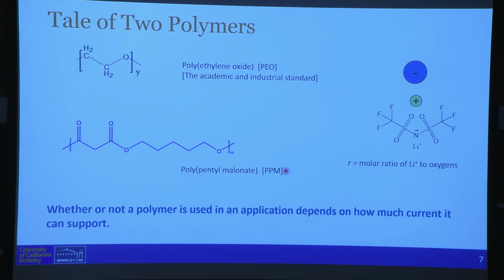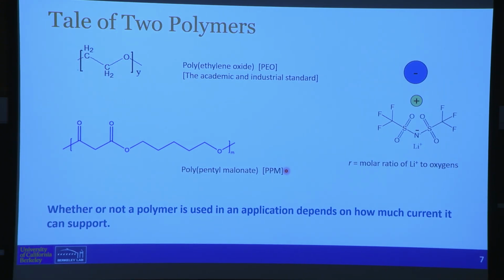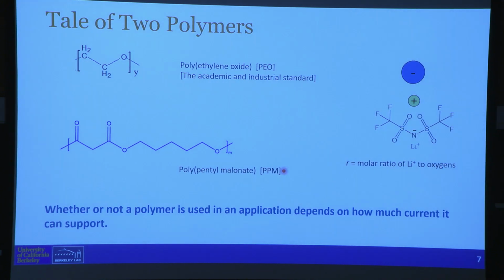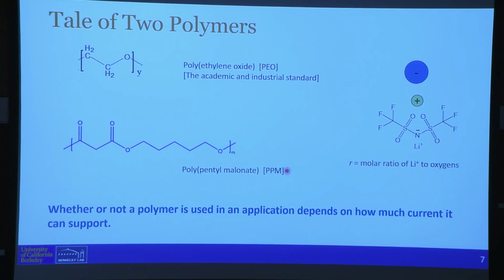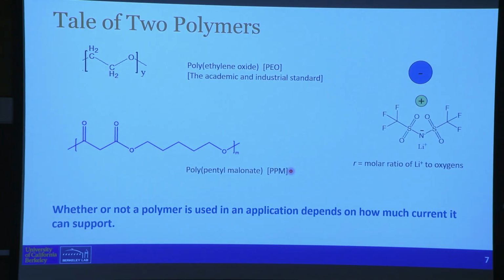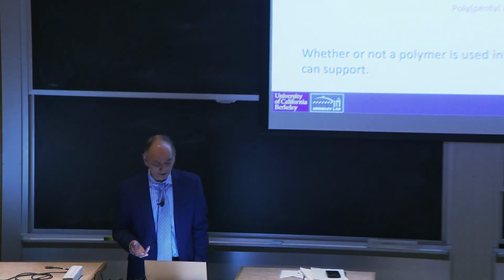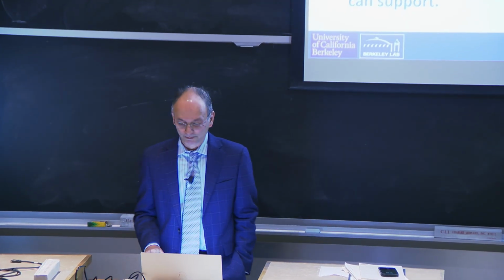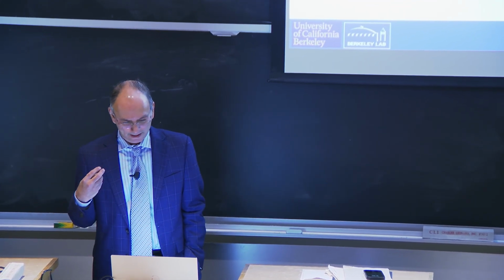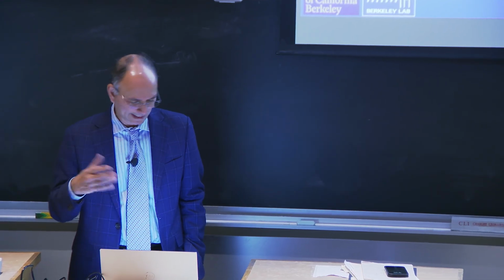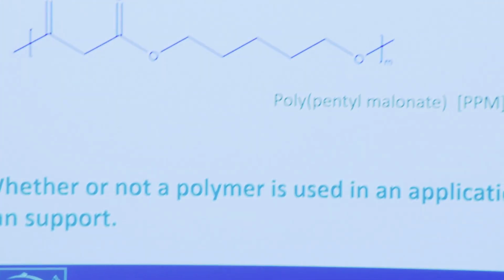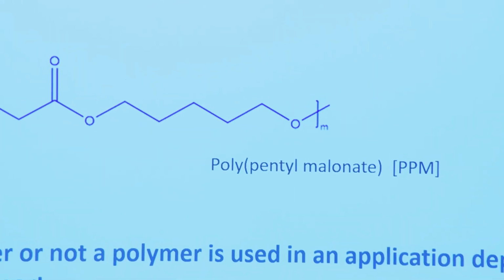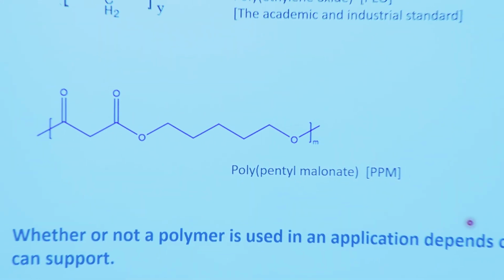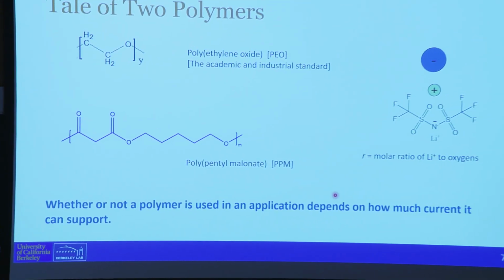And I'm going to tell you about 2 polymers. Okay. One of them is polyethylene oxide. There's a small industry that uses polymer-based batteries, and polyethylene oxide is what's in those batteries. And then I'm going to tell you about poly(pentyl malonate), or PPM. This polymer is something that we had a little bit to do with developing, but that's the structure. And the salt is lithium TFSI, so lithium plus with that structure carrying the minus sign.